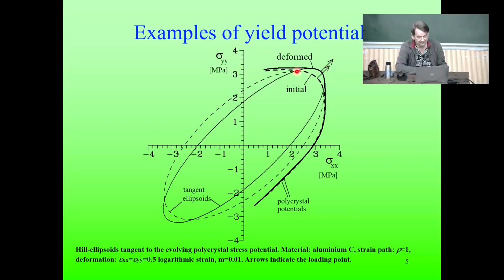You see how one can nicely fit this locally with an ellipsoid. Ellipsoid is very much elongated. It's not necessarily at 45 degree, because this is a textured material, anisotropic. It would be actually at the 45 degree, the ellipsoid, if it would be an isotropic material.